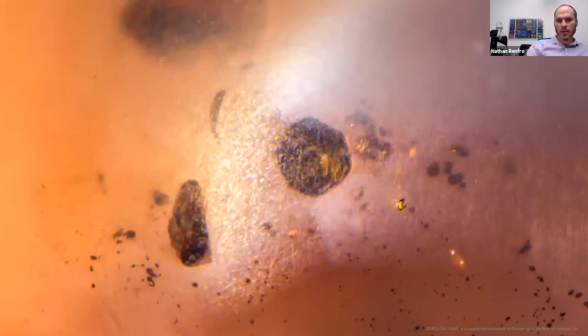Here's another example of silk. You often have these intricate zoned densities of silk. The core might have really dense areas of silk that become sparse as you go throughout the stone. It's not uncommon to have super-zoned layers almost like tree rings of silk in secondary Montana sapphires. This is an interesting stone — a pink sapphire from Eldorado Bar that has so much silk it's actually a star stone. Cut into a cabochon, it will actually show some weak asterism because there's so much silk.